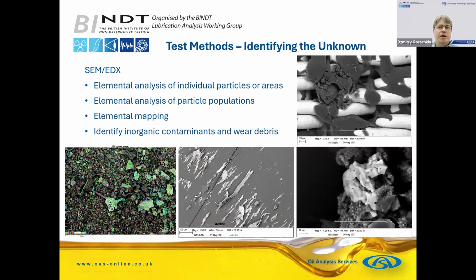So you can find out that we have 30% of the wear debris is of this metallurgy, which leads to a particular component. 20% is of a different metallurgy, so there's another component that's also wearing. And this works for inorganic contaminants, wear debris, that sort of thing.